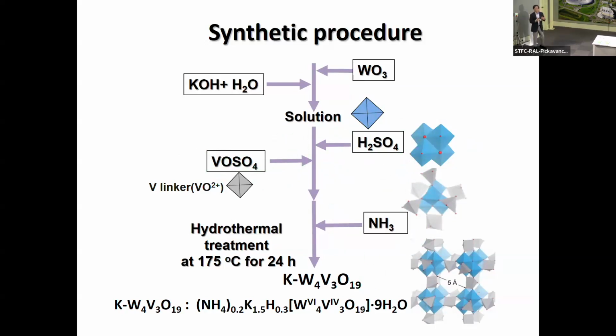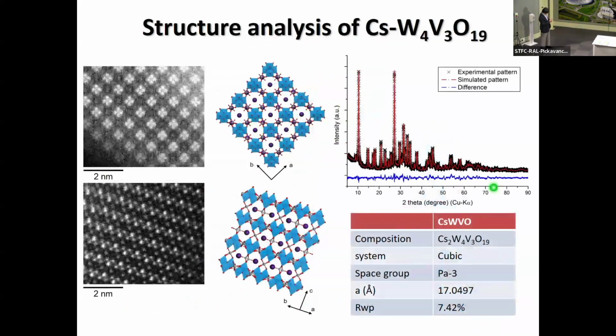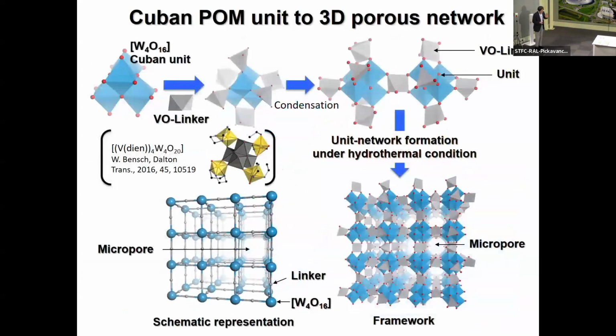Then after adding ammonia, which plays the role of a structure directing agent, we start hydrothermal synthesis at this temperature for 24 hours. Then you obtain a three-dimensional solid which has a porous structure. The structure is like this. I don't want to go into the detail. From this kind of information, we can confirm the formation process shown here. First, the Cuban unit reacts with vanadium, and then forms this one. This species has already been reported in the literature, which is a simple soluble inorganic complex. But after applying hydrothermal conditions, these species react together to form a three-dimensional solid with micropores.